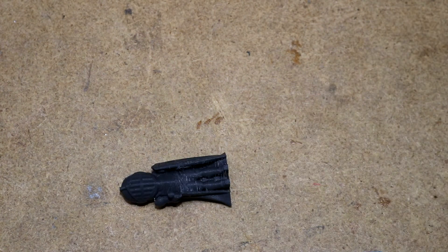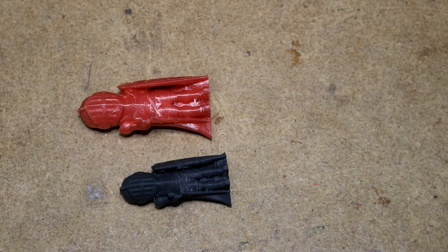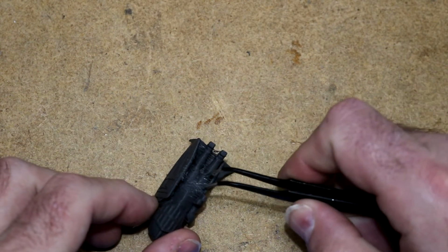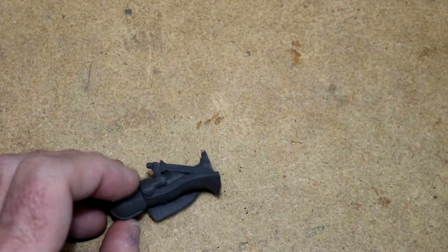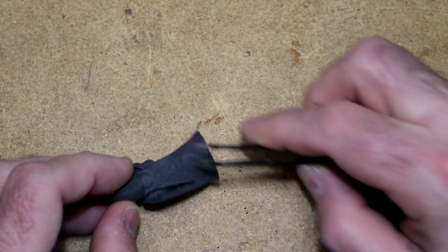And finally, I have Sir Layers A Lot. Usually I print these at 60%, but I ran a little short on filament, so he's a little bit short at about 49%. Here's a normal one in comparison, so you can see I had to print him quite a bit smaller than usual. You can see some stringing in here. There were also a few blobs in places that I could scrape off with my fingernail. They're hard. Maybe lowering the temperature would help with the stringing and blobs. But overall the detail is great — I can clearly read the back of the cape.